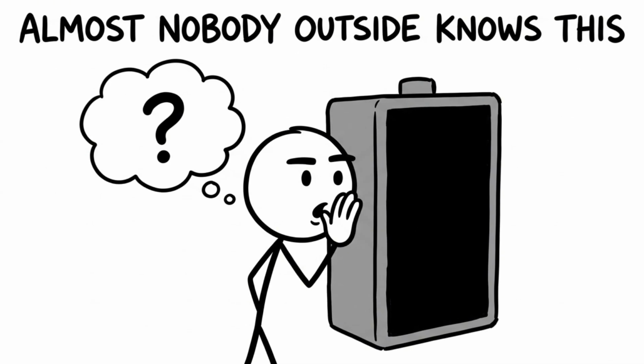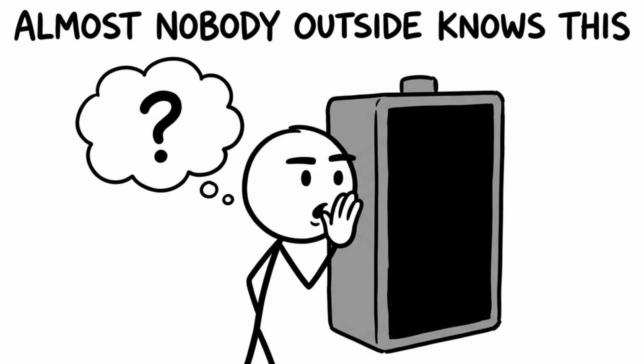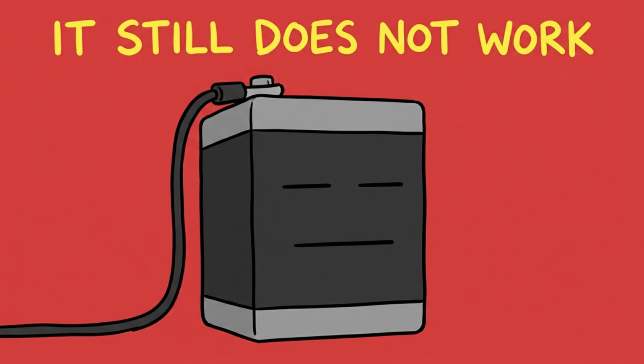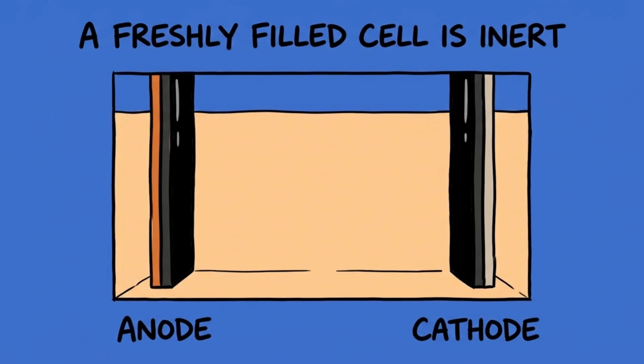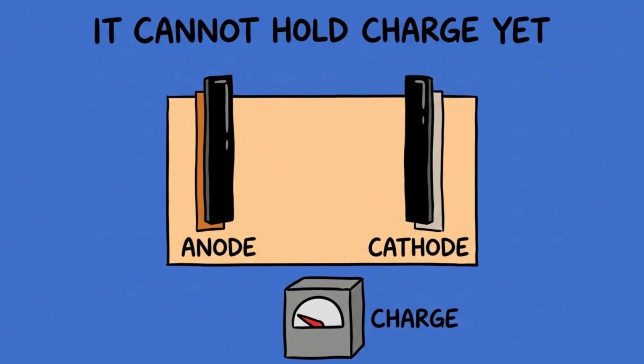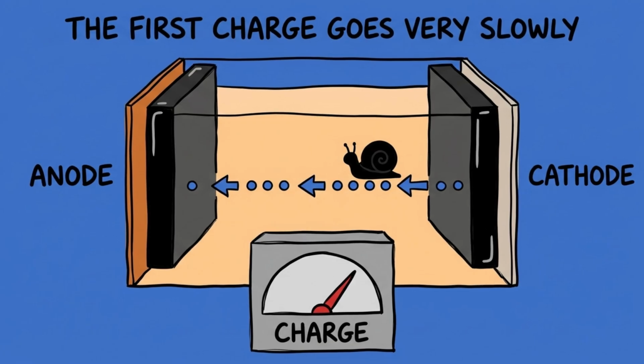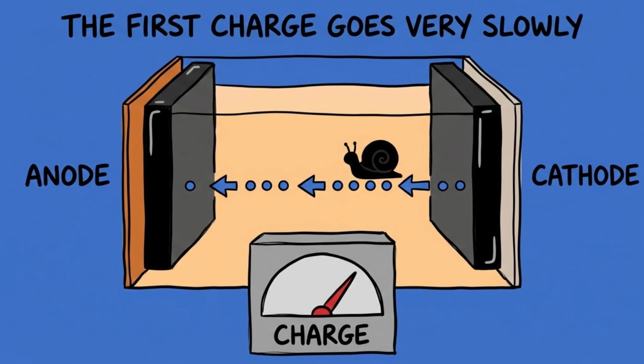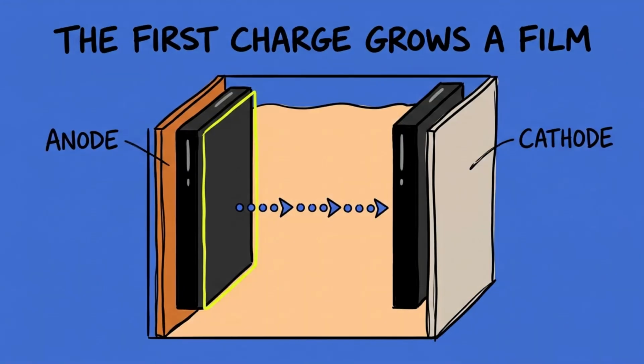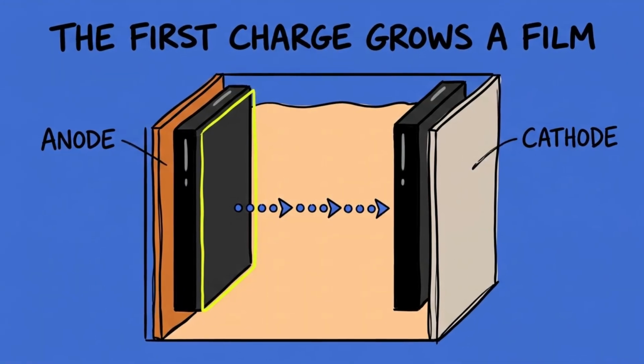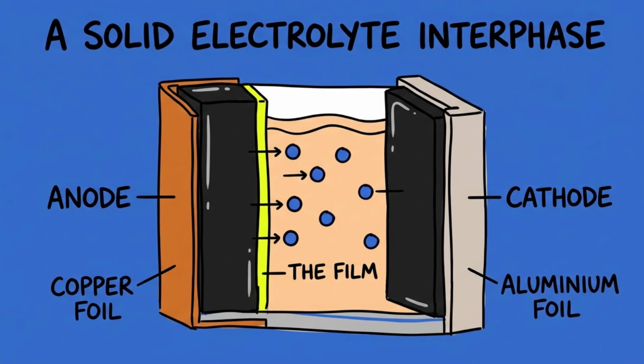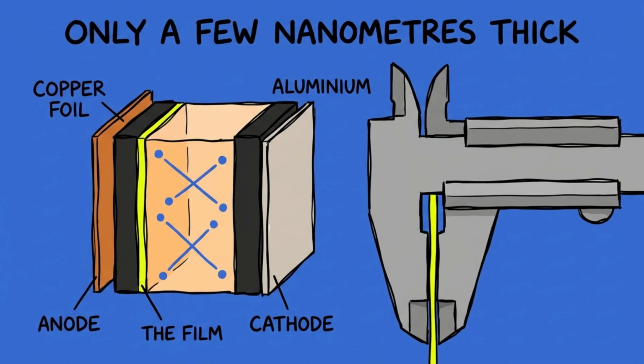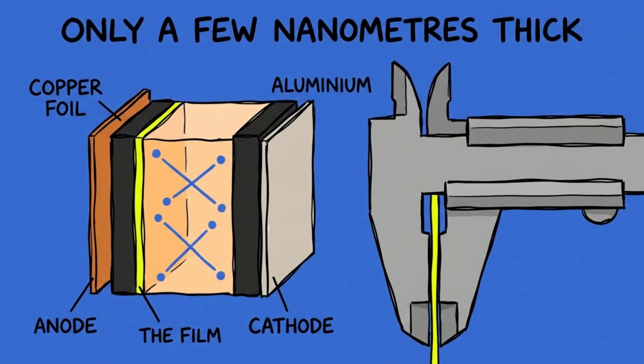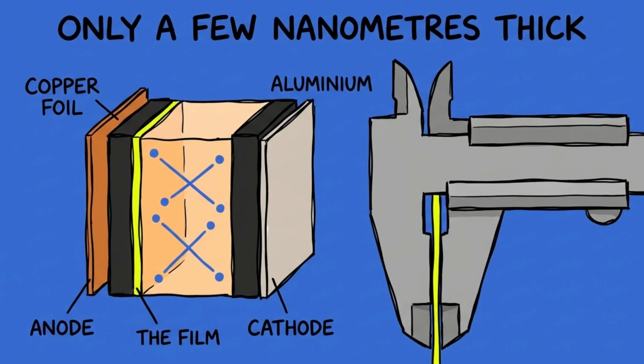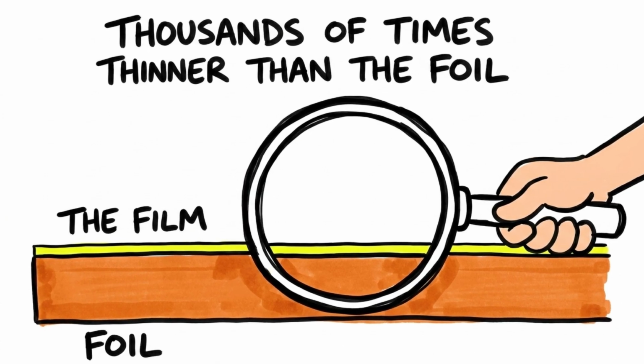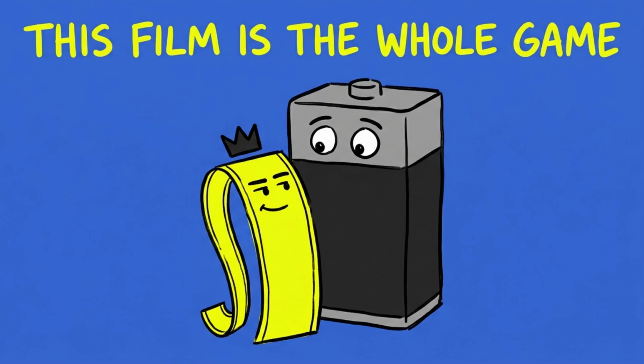And here is the part almost nobody outside the industry knows. It still does not work. A freshly filled cell is inert. Before it can hold charge properly, it has to be charged and discharged very slowly for the first time, under close watch. That first charge grows a film on the surface of the negative electrode, a solid electrolyte interphase, and it is reported to be somewhere around 5 to 20 nanometers thick, thousands of times thinner than the foil underneath it. That film is the whole game.